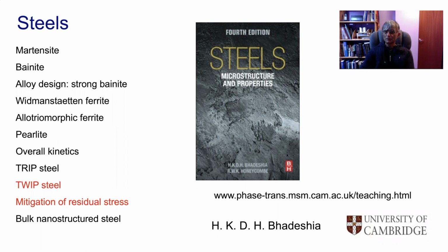But suppose that instead of martensitic transformation, we consider mechanical twinning as serving the same sort of function as martensite does in TRIP steels. And mechanical twinning has a much smaller shear than martensitic transformation, of the order of 0.07 as opposed to 0.26 in the case of martensite.